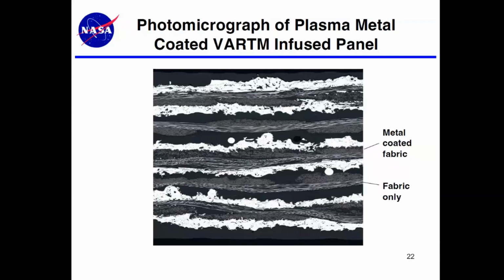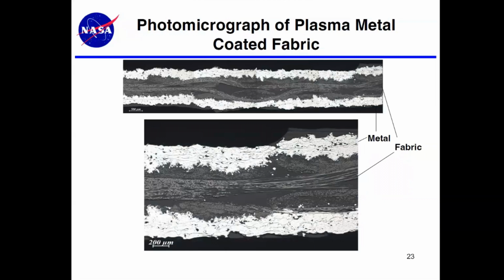What you're seeing here is one of the earlier versions. It's not a very high quality coating or very uniform coating. The next chart shows a material after we got a little bit better at the coating process. Again, we were able to set the parameters so that the metal layers were porous and then would be receptive to the VARTM process. Next chart.